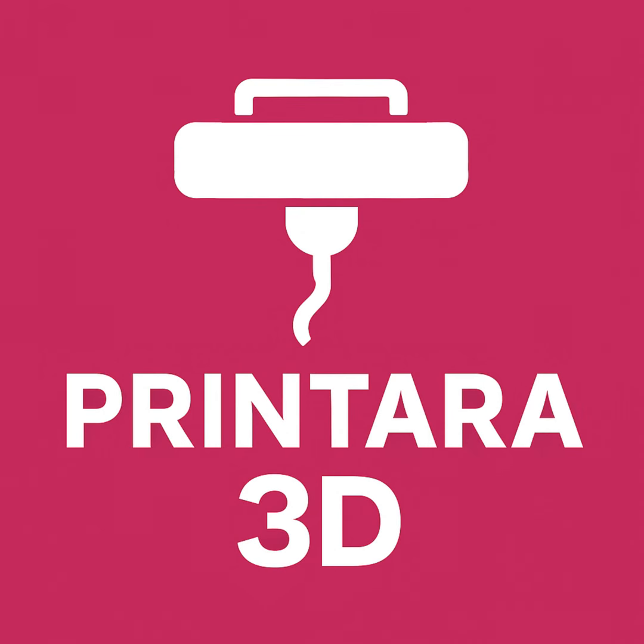3% does not sound like much, but plastic is incompressible once it cools. Over hundreds of layers, that excess 3% volume has nowhere to go. It bulges out the sidewalls, it scars the top surfaces as the nozzle plows through it, and on overhangs where there is no underlying support, it just sags heavily. This is why that hour of calibration is so powerful.